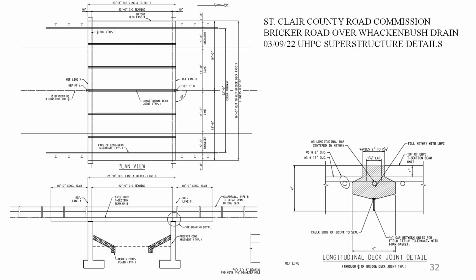On the right there, you can see the joint, the closure pour. The closure pour is quite small compared to traditional closure pours. And the reason is because the bond capability between the bar and the UHPC is so high. In our testing, we showed that for these bar sizes, you could get away with 2 to 3 bar diameters in terms of the transfer length. But in this case, of course, we used a much higher number.